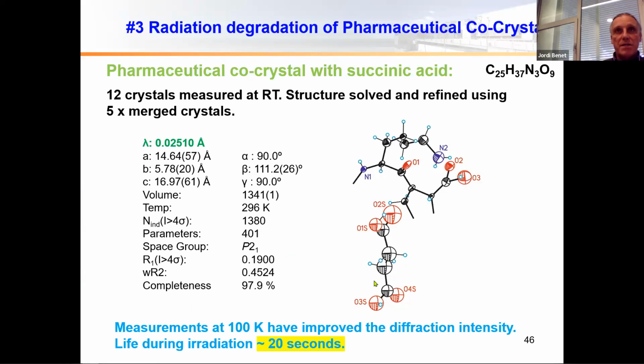So we could see the succinic acid, we could see the molecule which was forming this co-crystal, which is also cut, and we could also recognize where possible hydrogen bonds and contacts were, not because of the position of the hydrogen atoms, but because of the distance we observed between, let's say, oxygen atoms and carbon atoms or nitrogen atoms.